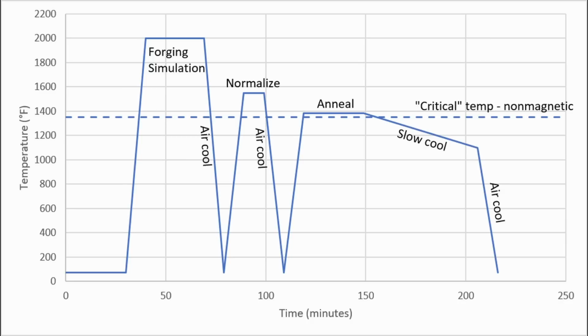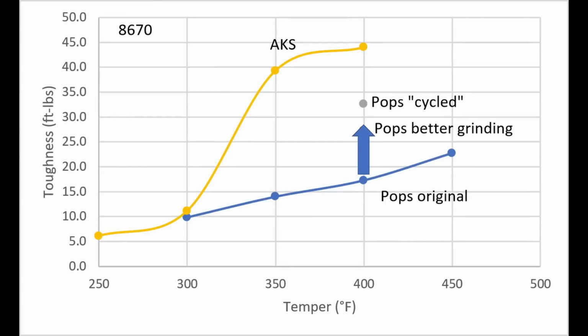So I eliminate the carbide structure of the steel as it comes from Pops, and I instead cycle it to give it a nice fine annealed microstructure that I know works very well, then heat treat it and test it. And it did get slightly tougher than the one that I had originally ground, but not so much to write home about. Maybe even if we did more specimens from both, they would be even closer together. Can't say for sure. But it's still not reaching the level of the Alpha Knife Supply material.